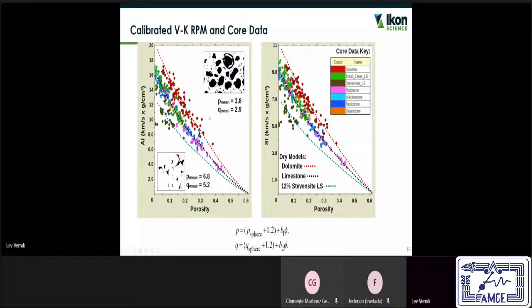So now let us put it all together. So here we show this data set that we have already discussed, the entire data set without any exceptions, separated by facies, or sometimes locations, and then we superimpose them with the Vernik model extending over the consolidated domain with the consolidation porosity of about 30% here, and then seamlessly continuing to the unconsolidated or poorly consolidated domain, ending somewhere around 60% porosity, which we believe might be considered a pretty good idea about the critical porosity of chalks.